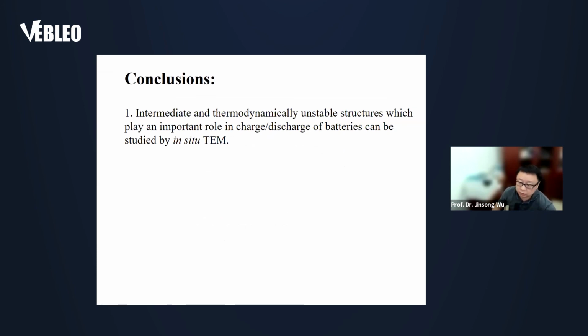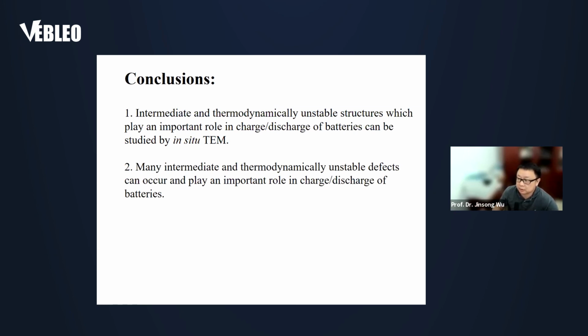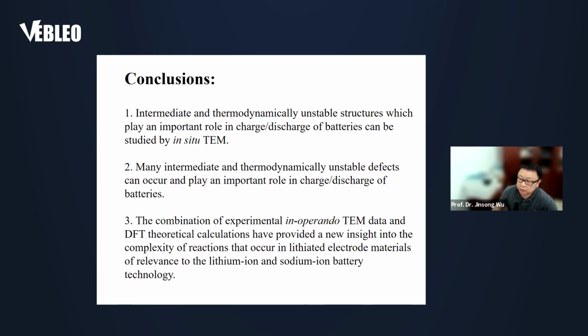Now it comes to my conclusion. The first one is that the intermediate and thermodynamically unstable structures which play a role in charge and discharge of batteries can be studied by using TEM. So TEM is a powerful tool to identify those intermediate and thermodynamically unstable structures. Those intermediate and thermodynamically unstable phases or structures are actually very important to the charge and discharge of batteries. And so the combination of experimental in operando TEM data and DFT simulation can provide new insight into the complex reactions. It can give us more information about what happened during the delithiation and lithiation.